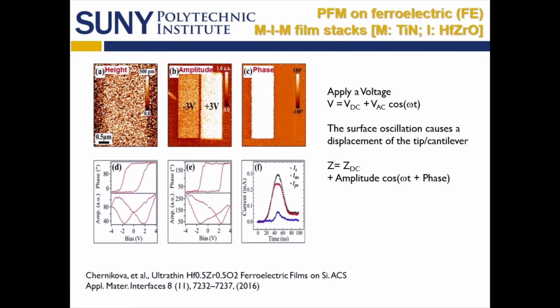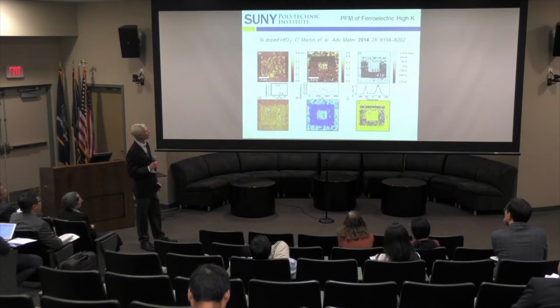All right, what's the interest here in AFM? Well, there's something called piezo force microscopy, which involves a conducting tip, and we got very excited when we saw some of the papers we're going to show you in the next couple of overheads here. That includes the fact that you should be able to tell from the amplitude maps and the phase maps, and here you apply a voltage with a DC and an AC component, and you can see an amplitude and phase in the surface deflection, and that should have a hysteresis loop in it in the amplitude data as shown here. And if you see that, that's a cool way to get information about the ferroelectric material.